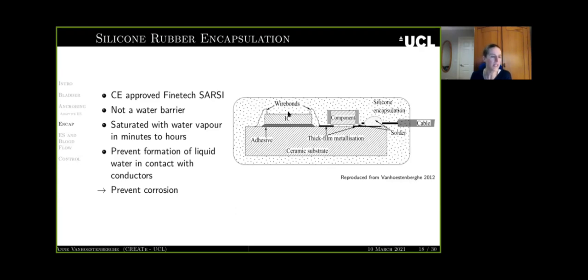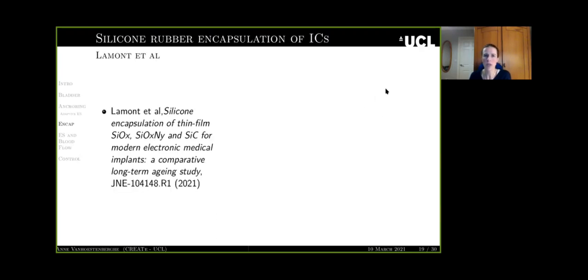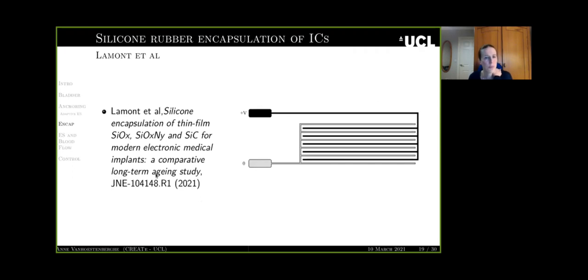but with passivation layers. And we did a study, which I will present to you today. Again, this is in the process of being published. Sorry, it's not out yet. And I will share with you details. It's a survey of silicone encapsulation on thin film silicon oxide, silicon oxynitride, and silicon carbide. And it's a long-term aging study.